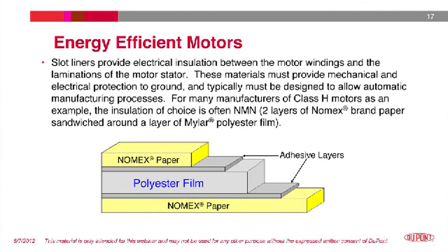Typically, this material is evaluated as part of an electrical insulation system, and for Class H motors, 180C, the insulation of choice is often NMN, two layers of Nomex paper sandwiched around a layer of polyester film, hence the name NMN. In this specific case, we decided to evaluate alternative slot liner materials to improve the overall life of the